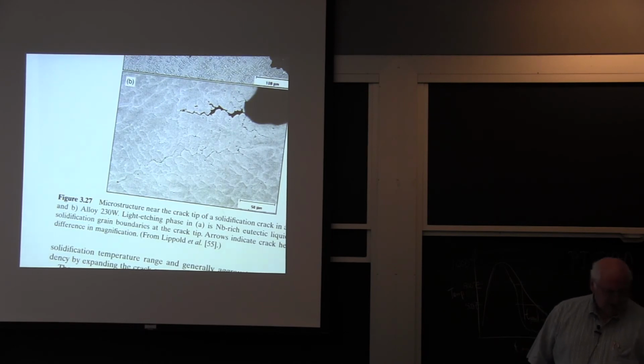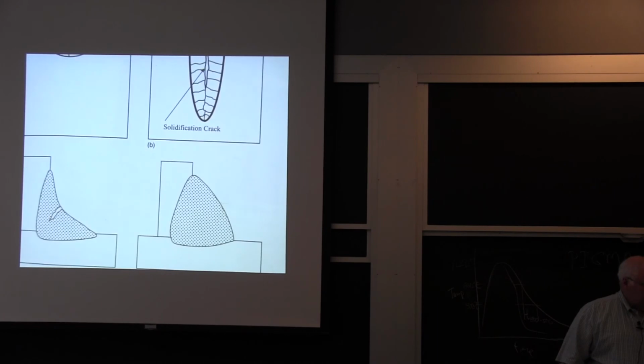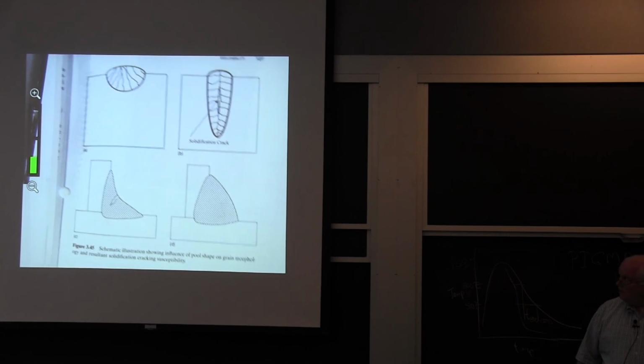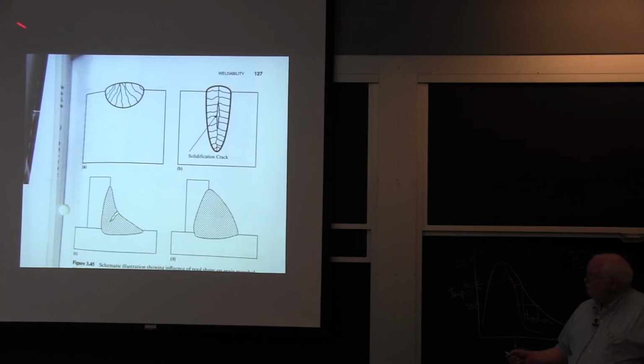Okay, so nickel alloys, whether they be Monels, whether they be Inconels, are very susceptible to liquation cracking, high temperature cracking, due to the stresses of shrinkage. So if I can make a weld like this, and I get all my grains going this way, it pushes all my alloy content there. If I make an electron beam weld, then I can end up solidifying grains from the edges in, and have all my alloy content in the center, and just have a crack right down the center of the weld. Okay, so the shape of the weld makes a difference.